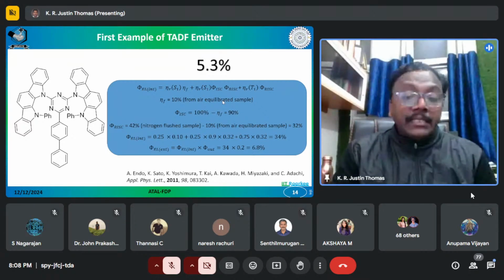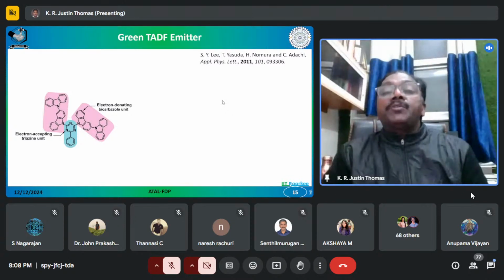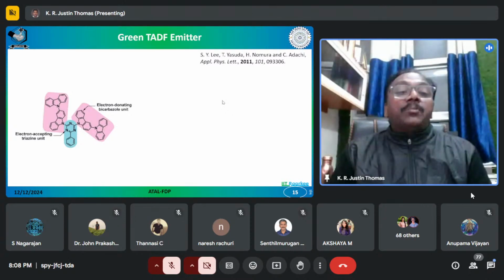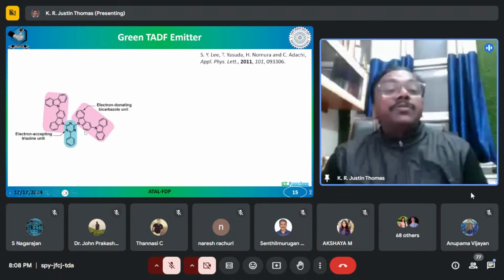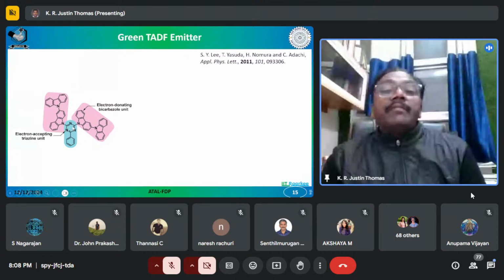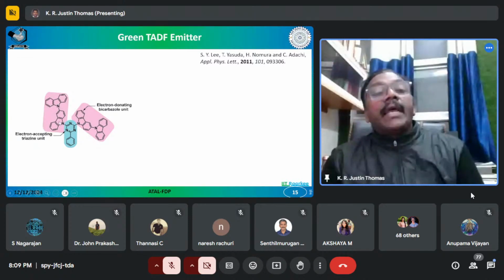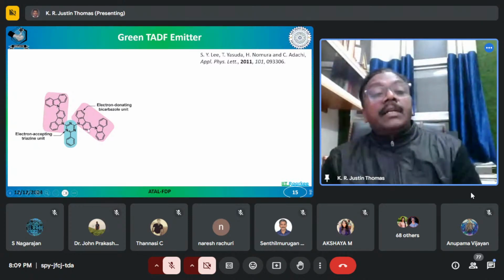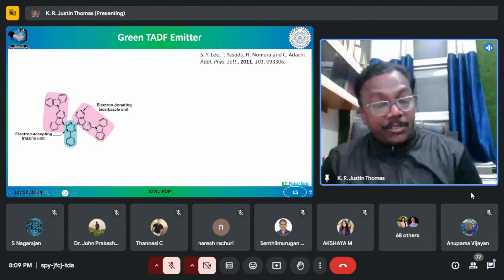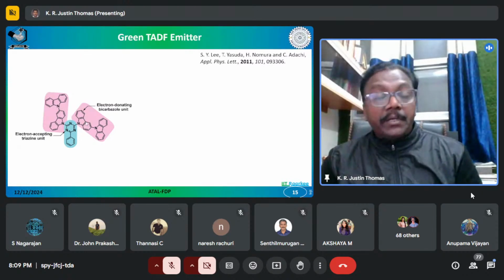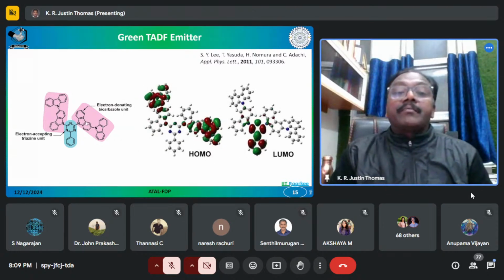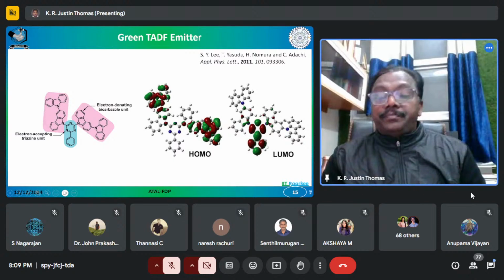And later, the Adachi group, the same group, reported another compound. It's an interesting compound as well. It was also in 2011. It's a green TADF emitter where they have used triazine as an acceptor, and they have used bicarbazole as a donor. When they used only one carbazole, they found that it is a non-TADF material, a simple fluorescent material. But when they use bicarbazole, the donor strength is increased and the steric crowding is increased. That leads to a tilting and well-separated HOMO-LUMO and small delta EST. You can see here, well-separated HOMO and LUMO.